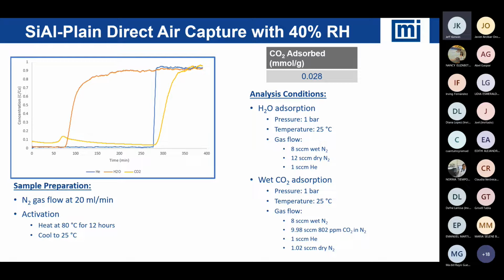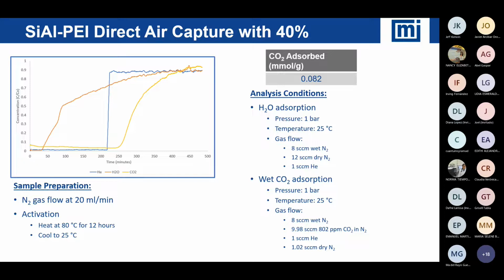Then in blue, you see the helium tracer gas, and then finally on the far right, you see the CO2 breakthrough. So we can calculate the CO2 adsorption in the presence of 40% relative humidity. So notice on just the simple silica aluminum material, there's very little CO2 adsorbed, 0.028 millimoles per gram. If you take that same material and then use it with the amine, right? So with amine loaded, we can increase the capacity, right? We have effectively tripled the capacity of the material just by using the amine rather than the pure silica aluminum.